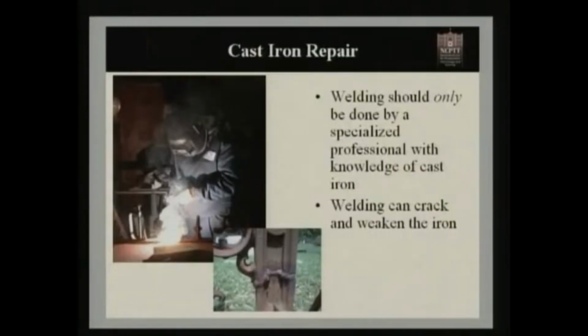Another way that we can do repairs is with heat, and that would be welding. Now, welding should only be done by a specialized professional with the knowledge of cast iron. Cast iron reacts very differently than any other iron type. Actually, the welding can crack and weaken the iron directly around the weld, and this is due to thermal shock. The temperature of the weld actually causes a shock and a cracking directly around it.